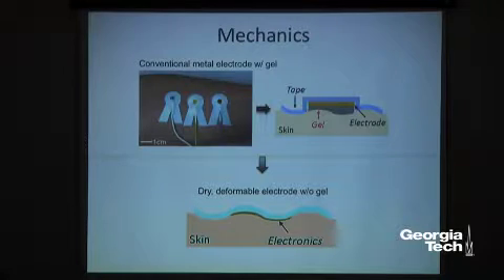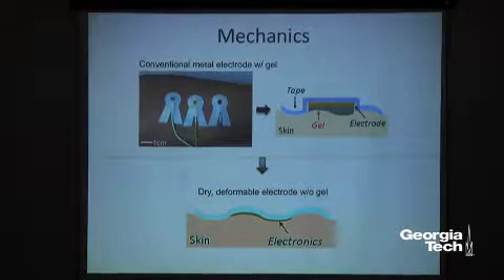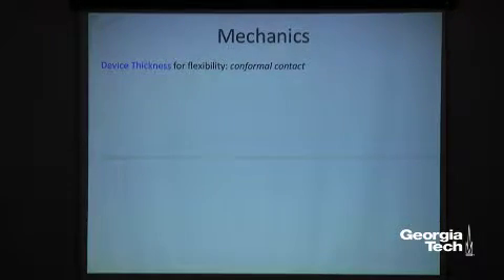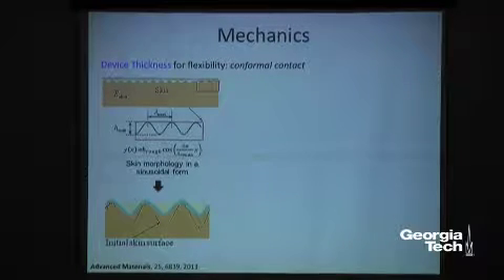Then somebody asked me how thin it needs to be, right? Should it be nanoscale thick, or microscale thick? That's a good question because it's really hard to make nanomembrane. So we calculated the ideal device thickness to have this flexibility, specifically to have intimate and conformal lamination over the skin surface. So we did a simple analytical calculation based on this skin morphology in a sinusoidal form.